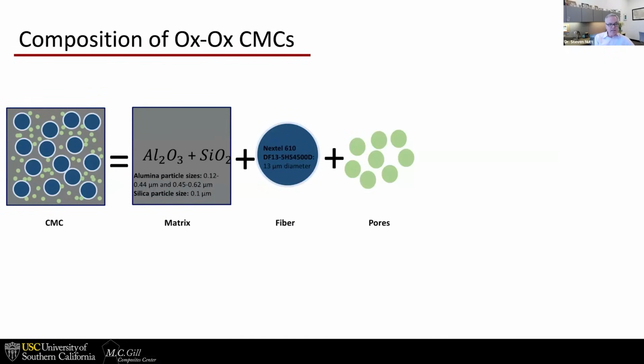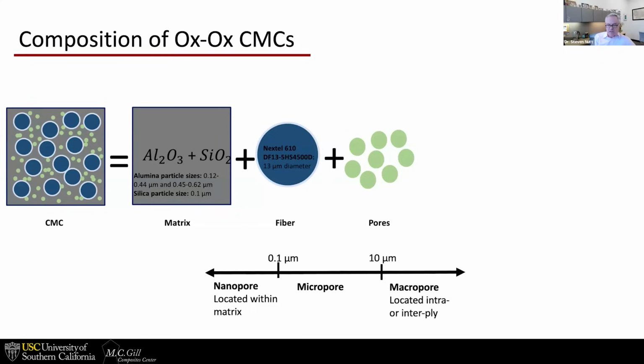Look at the Ox-Ox composites. The end product is on the left. That's a ceramic composite. The matrix is commonly either alumina or alumina plus silica powder, and then fibers made by 3M. Those are Nextel 610, 5 harness satin, 4500 denier, 13 micron diameter, and pores. So pores are part of the microstructure. Now the pores have a wide range of sizes. And therein lies part of the challenge.